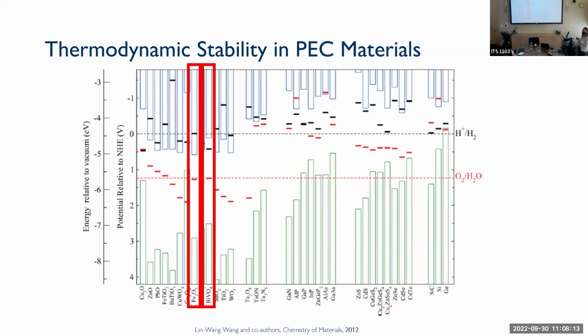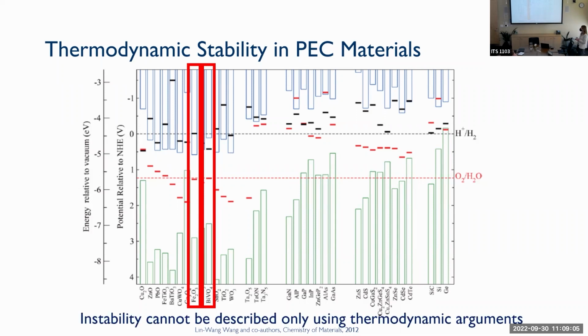However, if you look at a material that is known to be very stable, hematite, you know what's another name for hematite? I cannot hear, sorry. Rust, right? Do you know anything more stable than rust? So you look at the oxidation potential for water, and you look at the self-oxidation potential of hematite, they are also very close. So that could self-oxidize as well, but it doesn't. So it means that thermodynamics in this case is not enough to just explain why a material can oxidize. And there needs to be more consideration, specifically kinetic consideration, to understand what's going on to a material during operation.